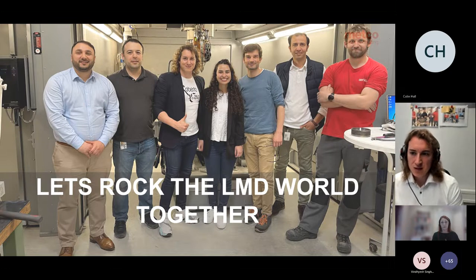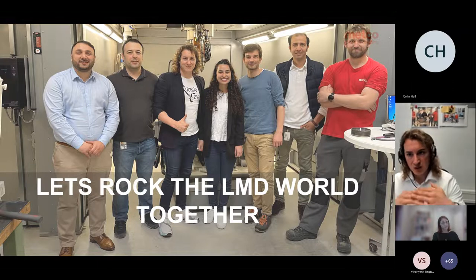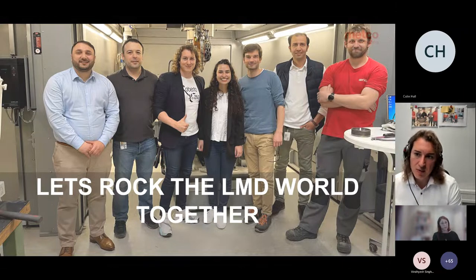So if we talk about cracking, in many industrial fields there is clearly a requirement to be crack-free. However, in other industrial fields, for example typical oil and gas, stabilizers, steering pads, ball valves, laser cladding is used already for more than 20 years. They solve it again with a bond coat, like they put Inconel 625 as a buffer, and on top they put this 60% volume tungsten carbide. I've learned recently that some companies like Laser Bond can do this type of components without cracking with this extremely high level of carbides.